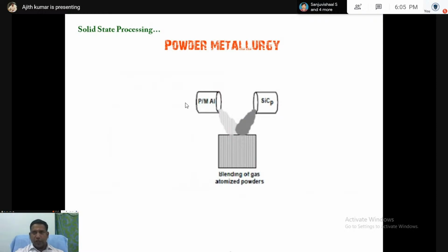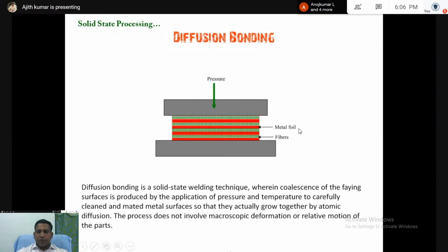We already discussed this using ball milling or mechanical alloying. We do this with aluminum and silicon carbide particles. If you have two different things, aluminum lumps or aluminum pieces with silicon carbide particles, we put both into the ball milling setup. Then we mix it for about 1 hour, or with respect to time if you vary, we can get the mixed powders. After that, if you press or compact, then after sintering, after heating, we will get the component. Then diffusion bonding. Diffusion bonding means one fibrous layer and one metal foil will be there. After that, if you press it, we will get the composite, because the metal will infiltrate into the fibers, then we will get the composite.